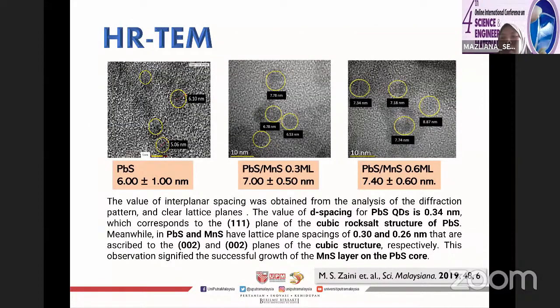So here are the HRTEM images. They show the different sizes of the quantum dots. The first image refers to the PbS quantum dots, where the size is about 6 nanometers. When we add the manganese solution, the size of the quantum dots increases compared to the PbS quantum dots. So here we can see that the manganese shell layer was formed, and the thickness was controlled by the amount of manganese that we add to the PbS solution.